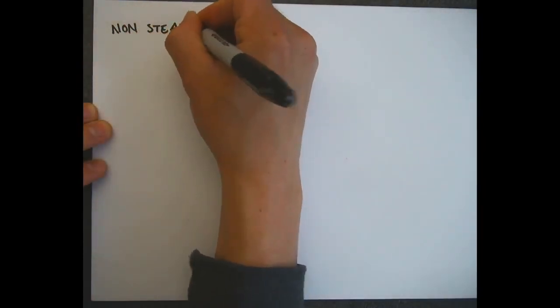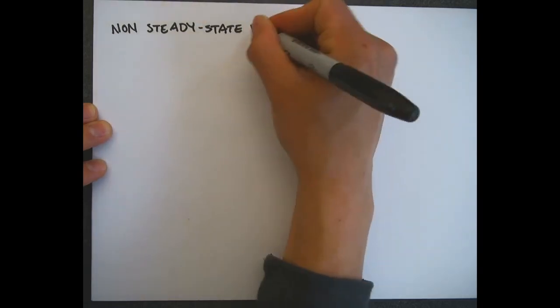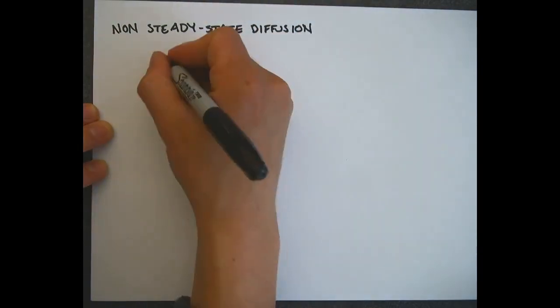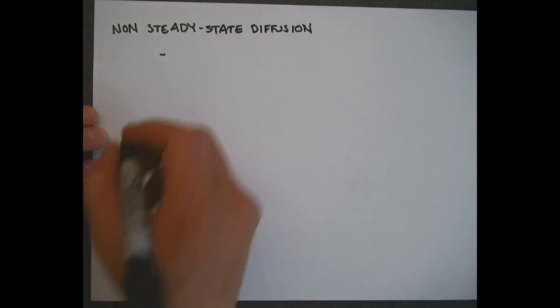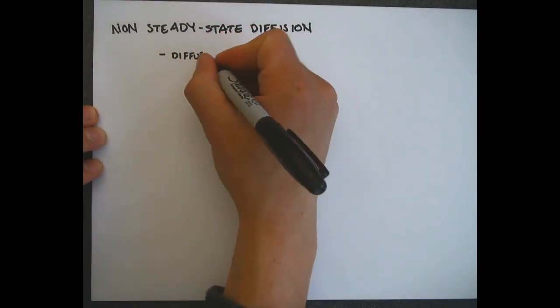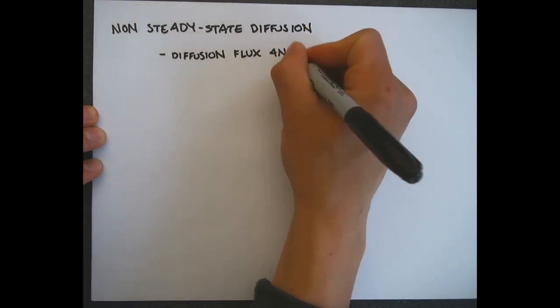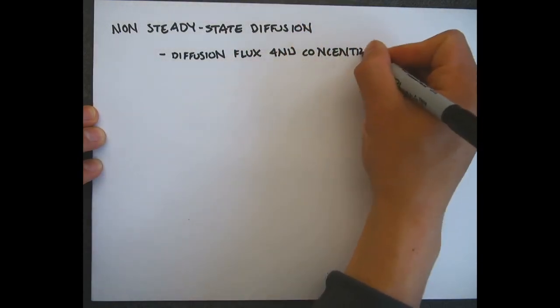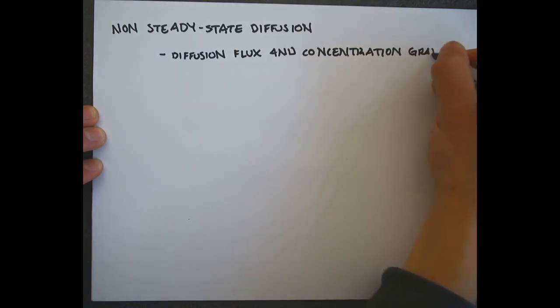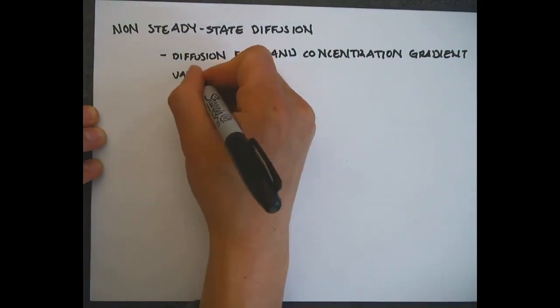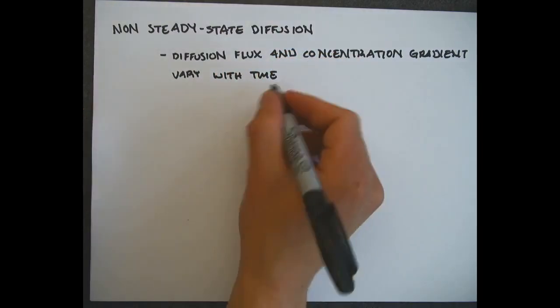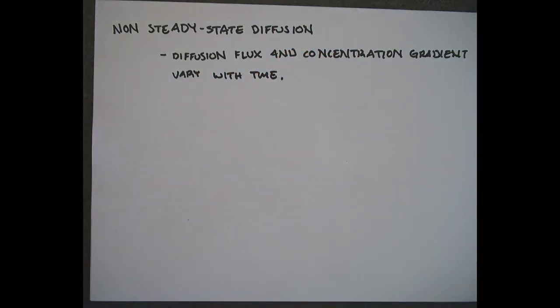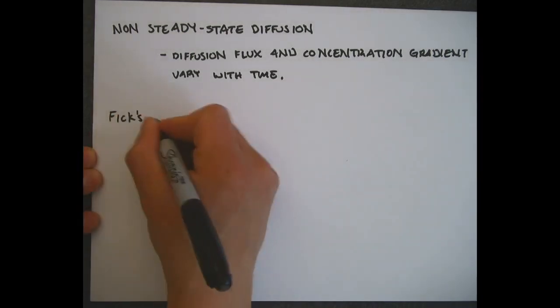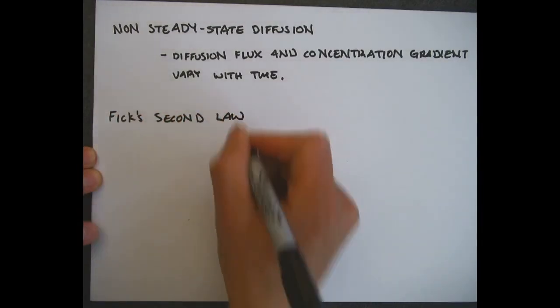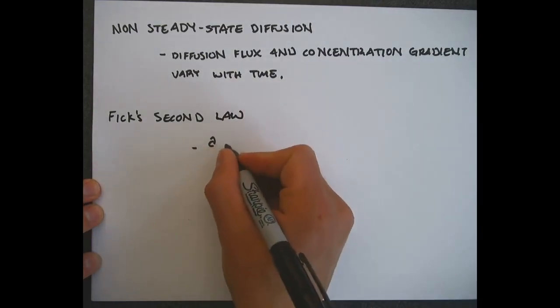Now we are going to discuss non-steady state diffusion. As you can tell, non-steady state diffusion is going to differ from steady state diffusion. If you recall steady state diffusion, the diffusion flux and concentration gradient were both fixed or looked at as constants, while in non-steady state diffusion, the diffusion flux and concentration gradient at some particular point in a solid vary with time. This just means as time goes on, the diffusion flux and concentration gradient will change. Now, this is going to lead us to Fick's second law, because these two conditions are changing. Fick's first law is no longer convenient to use.